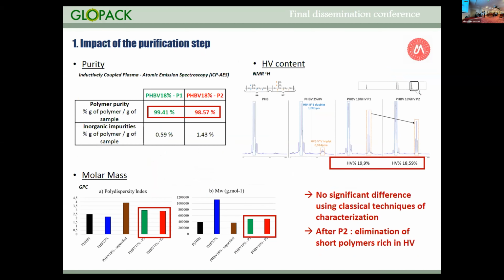second round of purification. And we see that using classical methods of characterization, such as molar mass, in fact, it was not so much impacted. But if we carry out some in-depth characterization using very advanced techniques, we see, and it was quite surprising, that after a second cycle of purification, the purity is decreasing. But why is it decreasing? It is because you increase, in fact, the content of inorganic compounds that can act as nucleating agents.